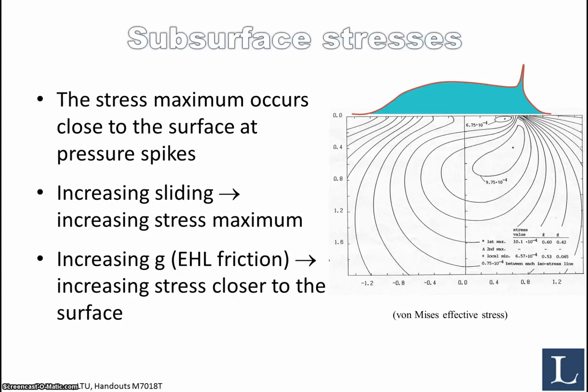Speaking of subsurface stresses, that means the stress that will occur in the material and not at the surface. And the stress maximum will occur close to the surface at the pressure spikes, somewhere in this region. And if you increase the sliding in the bearing, you will also increase the stress maximum. And increasing the EHL friction will increase the stress closer to the surface. And this becomes important when we will be discussing wear and failure of the bearings, since if the stress maximum coincides with some dislocation or some other impurity in the material, you can have crack nucleation and propagation of cracks.